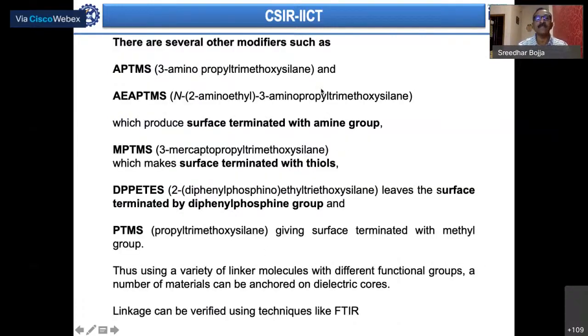So these are some modifiers, like 3-amino-propyl trimethoxysilane. By using these as your modifiers, you will have the surface terminated with an amine group. Similarly, if you want the surface terminated with thiols, you can use something like 3-mercaptopropyl trimethoxysilane. In this case, thiols will be your functional groups that are on the surface. If you want diphenyl phosphine as your terminating agent, depending on what you have done, you can do that.